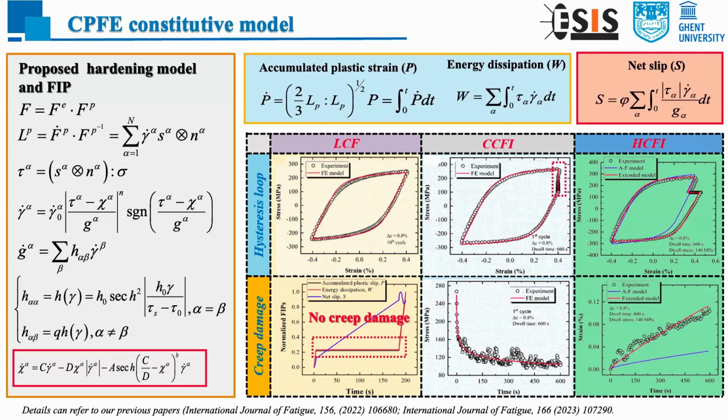So we also extracted the 3 damage parameter evolutions during this loading cycle. And we can see during the dwelling process, there's no increment for the first 2 parameters, so they can't capture the creep deformation. And this picture shows the stress relaxation during the dwelling. According to the 6th picture, we can see that our proposed model and damage parameter is very effective.